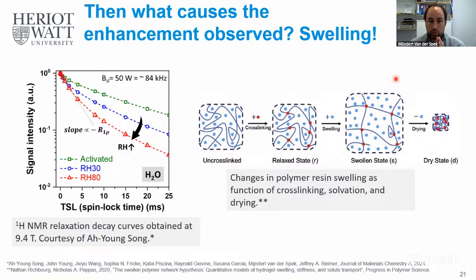So if you have only CO2, then the CO2 needs to do all that opening work, right? It's like blowing up a balloon. If you want to blow up a balloon, you need to put quite a lot of force on your cheeks and your mouth to blow up the balloon, right? So if you have only CO2, then the CO2 needs to do all that work. If you have water, then water does that work for you, and actually, because the whole mechanism of water sorption, including pore condensation, monolayer, multilayer adsorption, it opens up pores that were previously closed, and it just rearranges the polymer chains. So our current understanding is that this is what causes the enhancement.